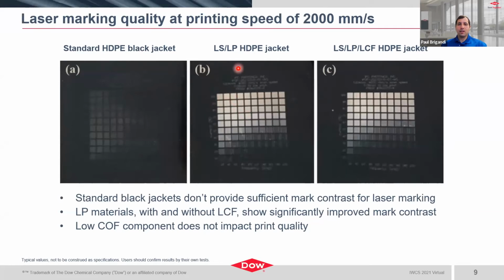The other key thing is actually the introduction, as I mentioned previously or alluded to, of the COF performance, which does not impede the ability to laser print these cables. So typically migratory additives to achieve COF, to reduce COF, may impede surface quality, whether it's ink or potentially laser. In this case, we're able to maintain that contrast.